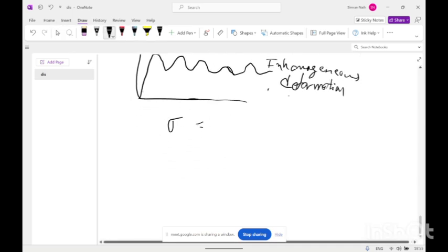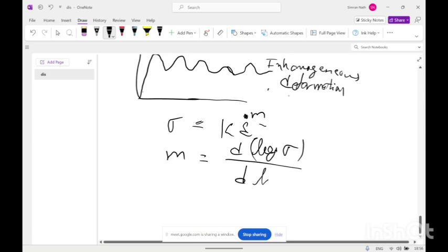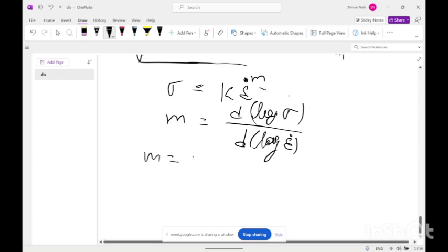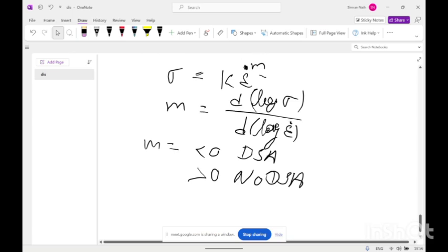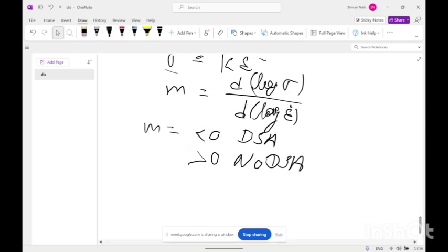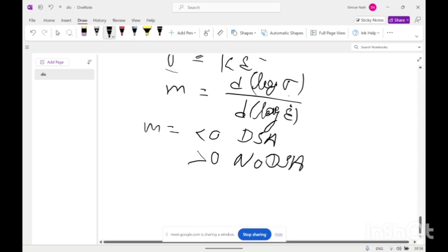So the stress relationship with the strain rate is this. If we want to find the strain rate sensitivity, we have to differentiate it in the log term. So m can be defined as d log sigma by d log epsilon dot. Here m is the strain rate sensitivity, and it is less than 0 in case of DSA, and strain rate sensitivity is positive when no DSA is there. The strain rate sensitivity means that with increasing strain rate sigma will increase, and in the DSA case when strain rate increases the applied stress will be lower.